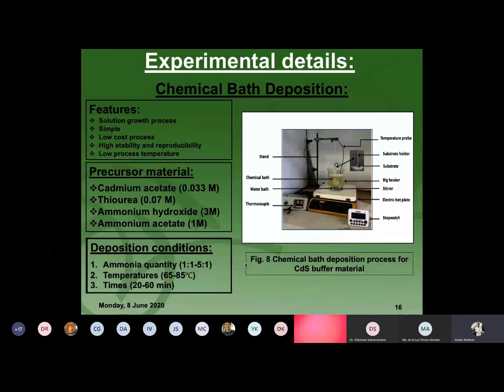The solution is prepared with 0.033 molarity of cadmium acetate, 0.07 molarity of thiourea, 3 molarity of ammonium hydroxide, and 1 molarity of ammonium acetate in 200 ml of water. I have deposited under different conditions: first varying the ammonia quantity, and then temperature and time.